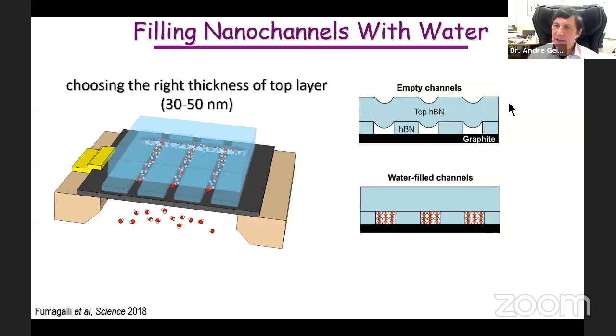So a kind of hand-waving explanation is that there is a van der Waals interaction, which is quite well known, between top crystals and side walls. It's observed by many groups over many years. And this makes the top crystal sag, whether it's single layer or multi-layers, the sagging always occurs. Water molecules somehow screen this interaction. We don't understand that, we don't fully know molecular dynamics simulations of this subject, but this is experimental observation, and we speculate that when water goes inside this space, it somehow screens the interaction of this crystal with this crystal. This is all I can say.